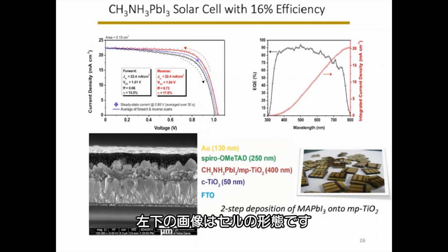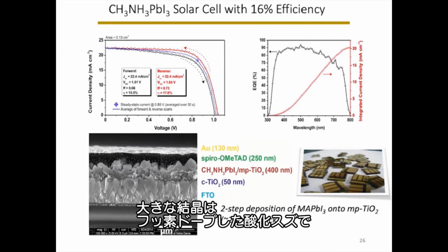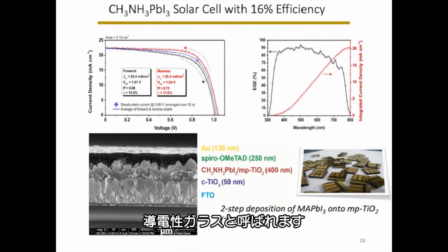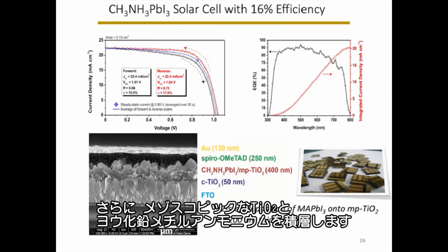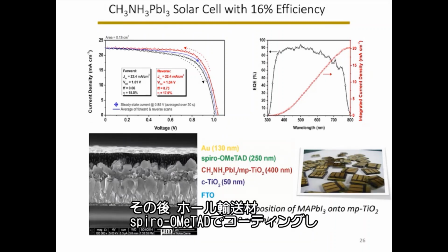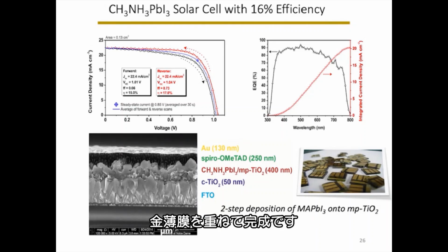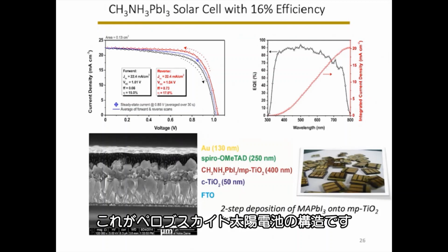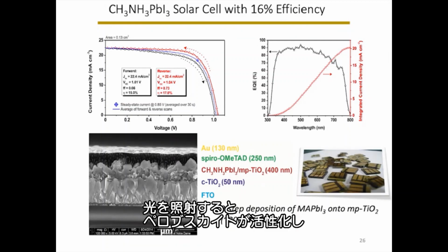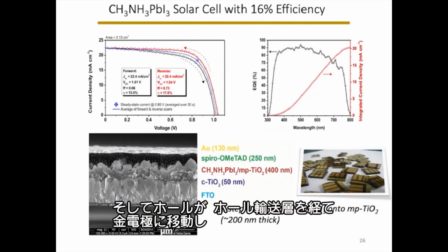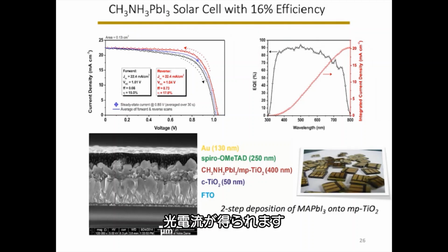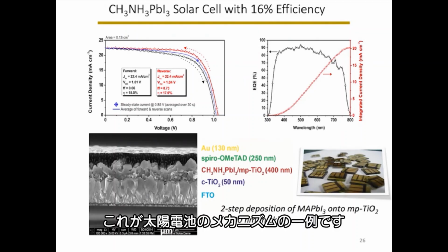The morphology of the cell you can see here in the bottom left corner. The large crystals are fluorine doped tin oxide, what we call conducting glass, on which we put a compact TiO2 layer followed by mesoscopic TiO2 and methyl ammonium lead iodide. Then we coat with a hole conductor, spiro-OMeTAD, and then you put a layer of gold, and that is it. So this is the anatomy of a perovskite solar cell. When you shine the light, the perovskite becomes active, the electron flows to the TiO2, and the holes travel through the hole conductor to the gold electrode, giving you the photocurrent in this system. This is just to give an example of how a solar cell works.